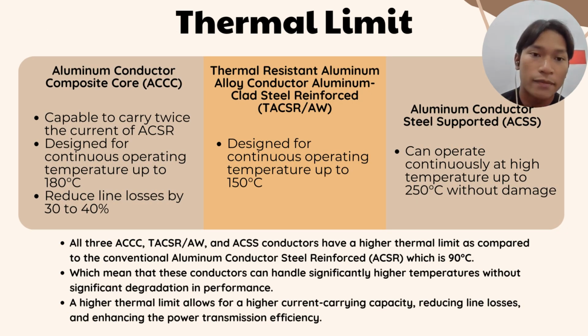Okay, now let's look at the thermal limit of these HTLS conductors. ACCC is capable to carry twice the current of ACSR, and it is designed for continuous operating temperature up to 180 degrees Celsius. It is able to reduce line losses by 30 to 40%. Second one is TACSR, which is designed for continuous operating temperature up to 150 degrees Celsius, while ACSS can operate continuously at high temperature up to 250 degrees Celsius without damage.